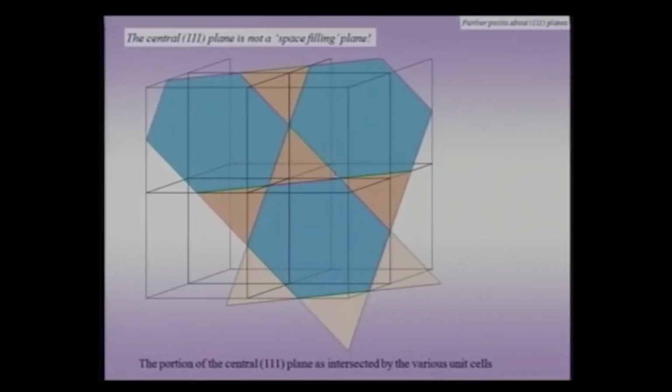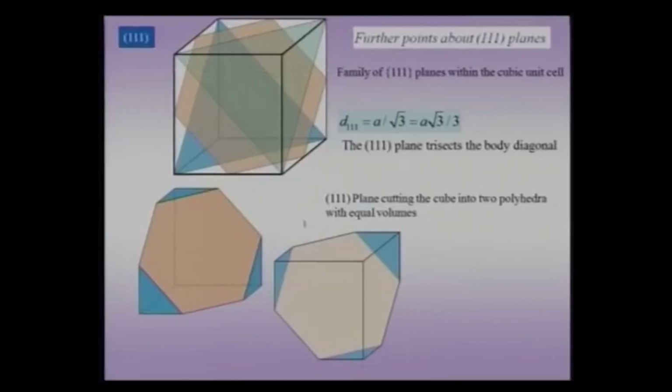Therefore, if I make my atomic density calculation or one of those calculations based on this kind of a blue 1-1-1 plane which is shown as a hexagon here, I will get my number wrong. So, this point has to be kept in mind, that I have to also additionally worry which plane in the unit cell I have to choose, and clearly the correct choice for this cubic crystal system would be the blue plane or the orange plane. And suppose I am talking about division of this polyhedra into a mid plane, then this orange plane is the mid plane which actually bisects my body diagonal.